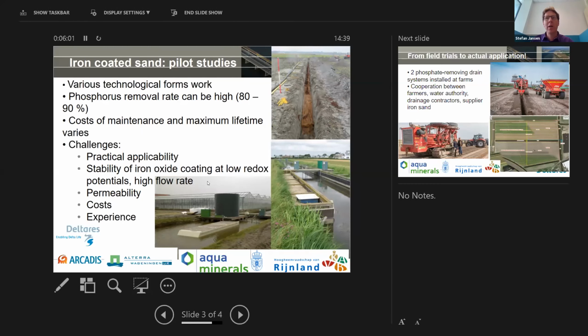A very important issue is the stability of iron oxide coatings at low redox potentials and high flow rates. Recently, we saw issues with these. For instance, that at low redox potentials, the iron oxide might dissolve or loosen from the sand grains, and it might lead to phosphorus remobilization. And well, permeability was already mentioned, and of course, costs and more practical experience are very important issues for further practical application.